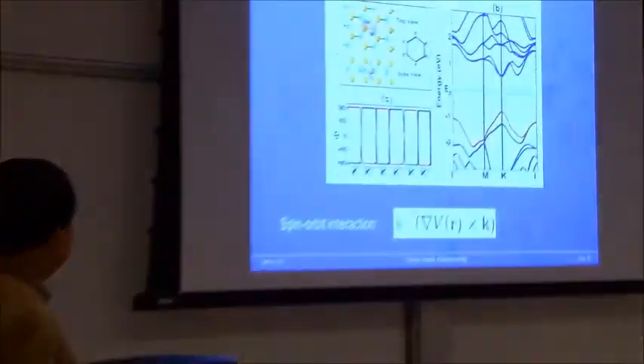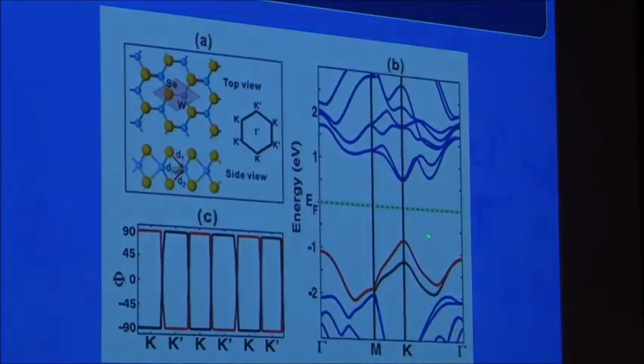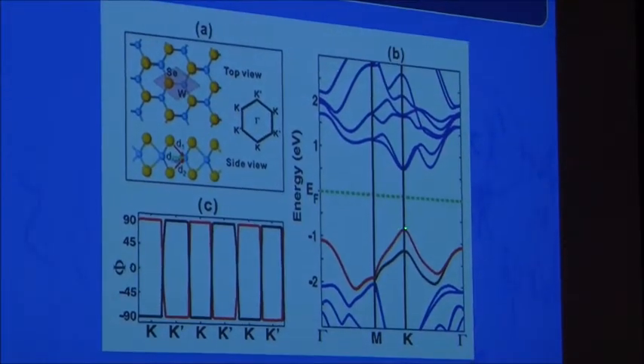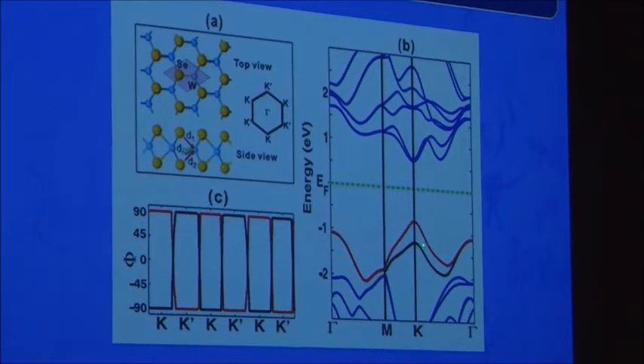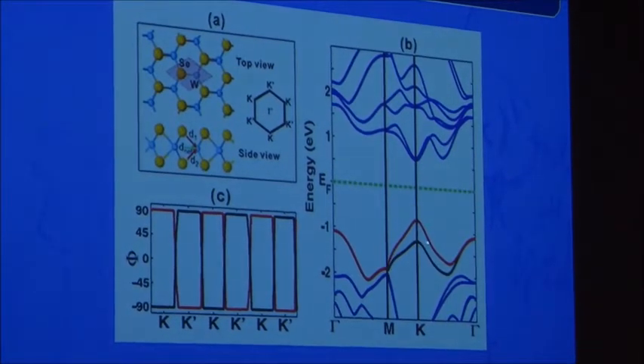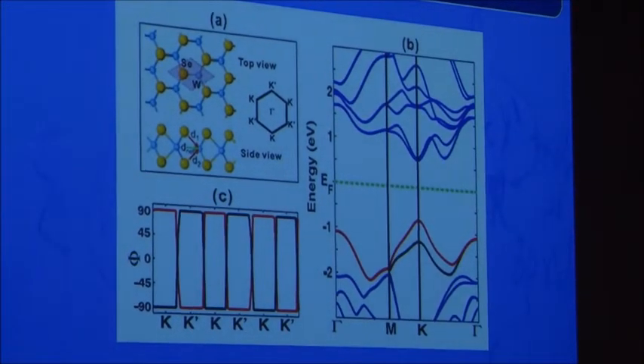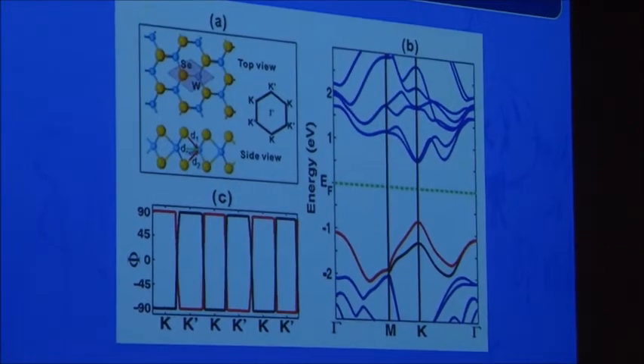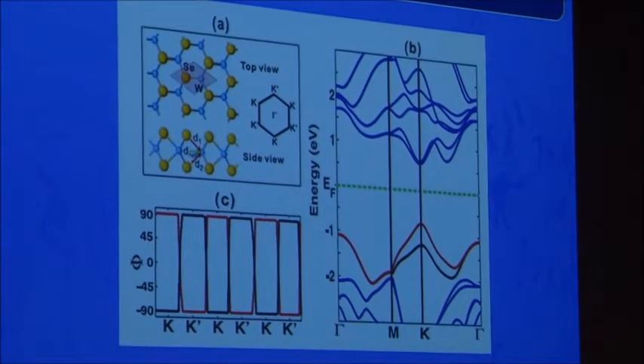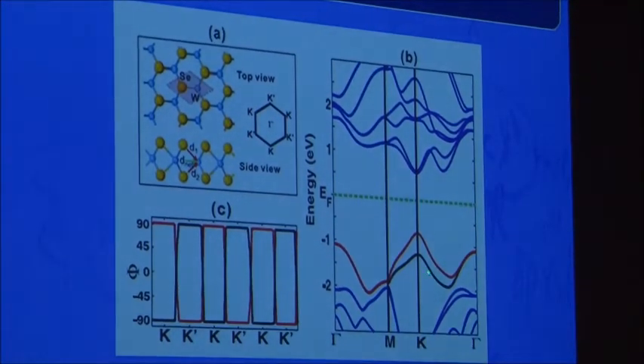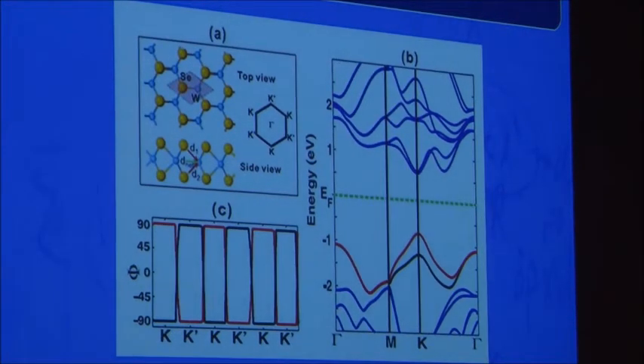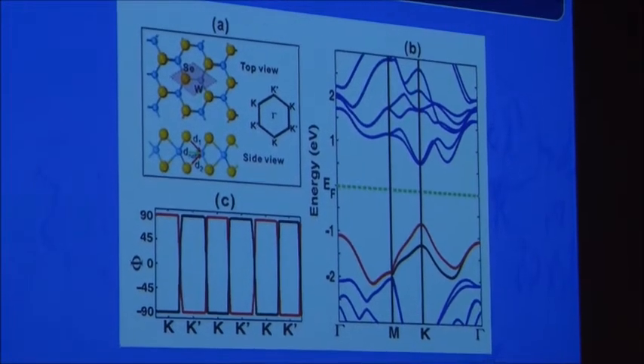This is the calculated band structure of this material, tungsten selenide, and you see that it has a direct band gap. I have a red and a black curve. This is splitting due to spin orbital interaction. Because of this heavy atom tungsten, you have very large spin orbital coupling, which gives you a splitting of about 400 meV. So this is very large.